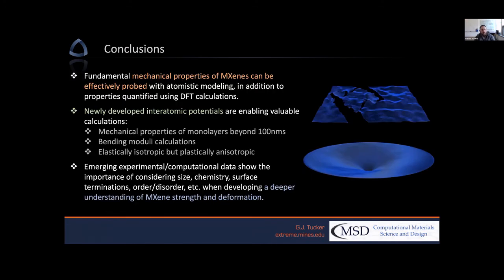So in conclusion, some of the fundamental mechanical properties of MXenes can certainly be probed with atomistic modeling, in addition to building upon all of the phenomenal work that's been done using DFT calculations over the past few years. And we believe that developing new interatomic potentials potentially is a way to actually do this, where we can reach larger monolayer sizes. We can look at bending moduli calculations as we showed. And then lastly, elastically isotropic but plastically anisotropic was one of the themes that we actually saw when we started to perform these mechanical tests of these monolayer sheets.